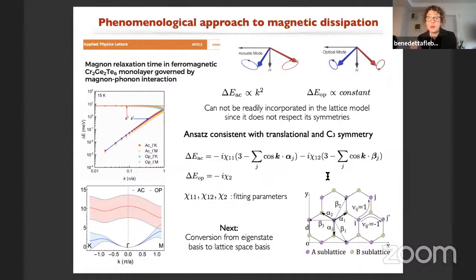And for the broadening, a very important point, of the eigenmodes, we make this ansatz, and here our chi's are fitting parameters to their results. So we make such an ansatz, and then we fit the ansatz to their result, and we have three fitting parameters, so it's a pretty good fitting. Now the question is, what are these terms?